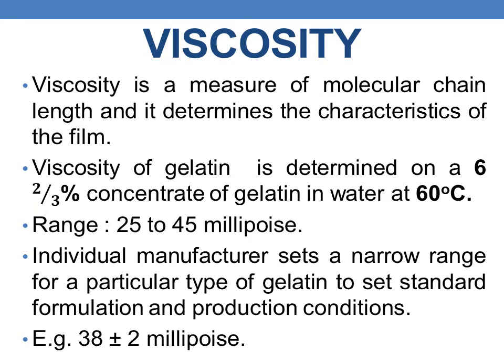Coming to viscosity: viscosity is resistance to flow. In the case of gelatin, viscosity is the measure of molecular chain length and it determines the characteristics of the film. Viscosity of gelatin is determined on a 6⅔% concentrate of gelatin in water at 60 degrees Celsius. The range is 25 to 45 millipoise. The individual manufacturer sets a narrow range for a particular type of gelatin to set standard formulation and production conditions — for example, 38 plus or minus 2 millipoise.